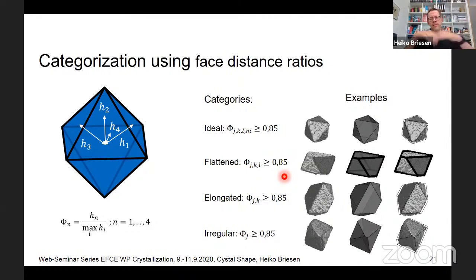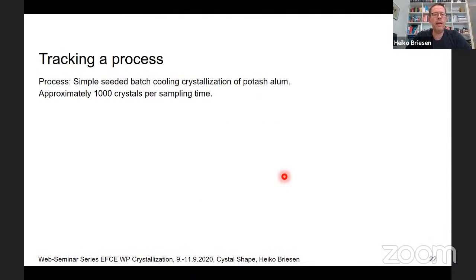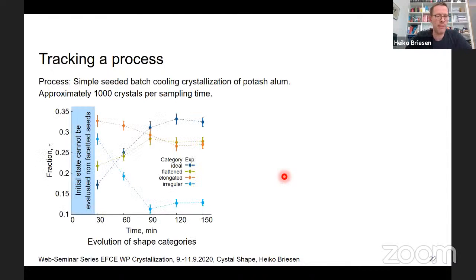So what we did now with this data set here, we took a process, a seeded batch cooling crystallization. I spare you the details of the experimental procedure. We took samples about every 30 minutes and did a characterization of approximately 1,000 crystals per sampling time. So you end up with something like this, and the different lines you see here are the different shape types: the ideal, the flattened, the elongated, and the irregular one.